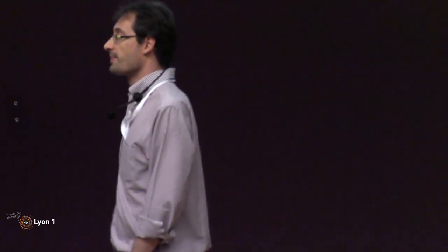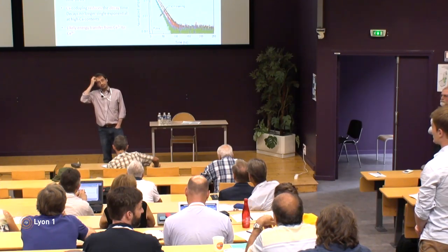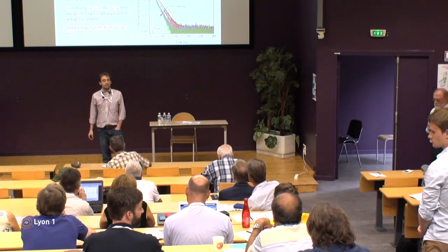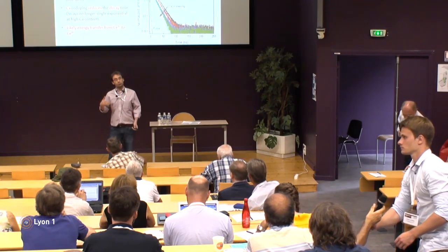Could you comment on the origin of the absorption associated with cerium 4+? In cerium 3+, the absorption is related to the 4f-5d transition. What happens in the case of cerium 4+, where there is no f electron? No, there are no f electrons, but what you can have is the charge transfer from a ligand to the cerium. This is quite well known as a mechanism.